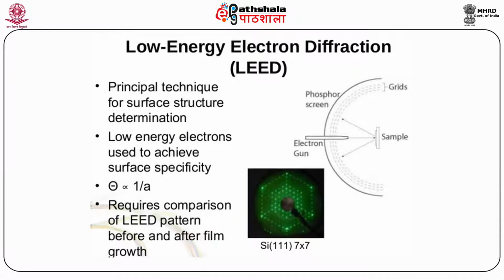To understand a lot of physical and chemical properties of solid substances, the knowledge of solid structure is very important. It is important for explaining phenomena in heterogeneous catalysis, microelectronics, etc. There exist a lot of methods to determine the surface structure. One of the most popular is LEED. In LEED, we investigate elastically scattered electrons. Typical energy range in LEED is 30 to 500 electron volts.